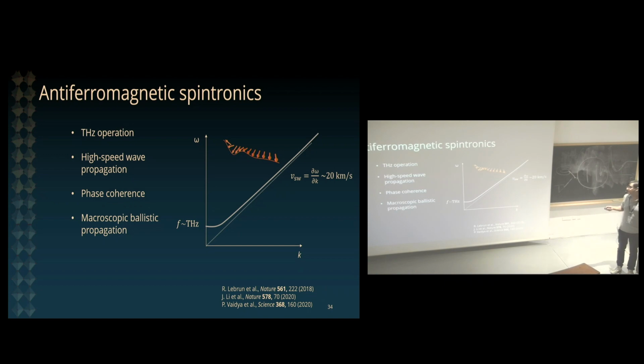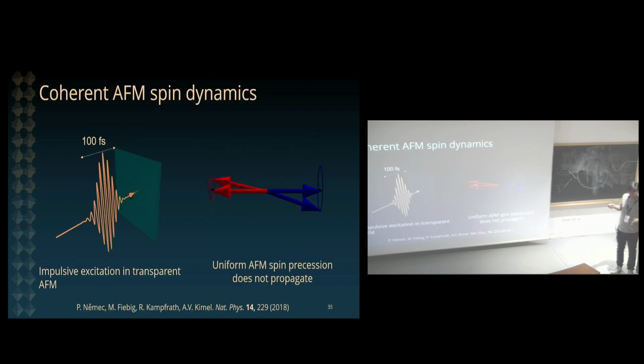So we have antiferromagnets that in principle would allow us to process information at terahertz frequencies. They are characterized by a spin gap, which is set in antiferromagnets in the terahertz range. Moreover, the dispersion of these systems tends to a linear behavior as we go to the edge of the Brillouin zone, with a characteristic group velocity of the order of tens of kilometers per second. In principle, these are objects that would allow us to transfer information very fast and possibly even in ballistic propagation. And there's a lot of research, and yesterday it was nicely reviewed.